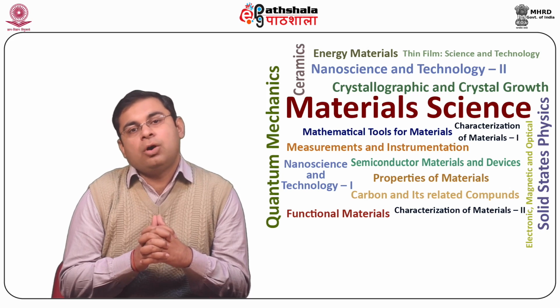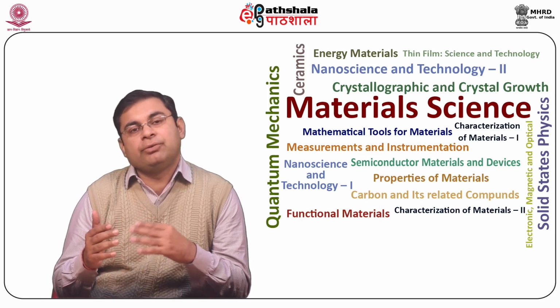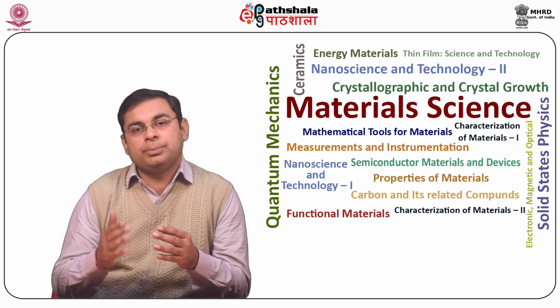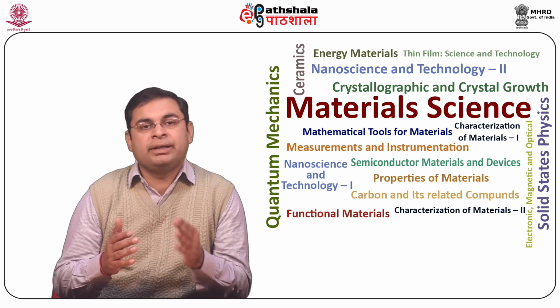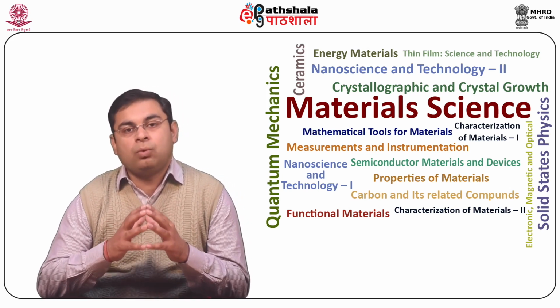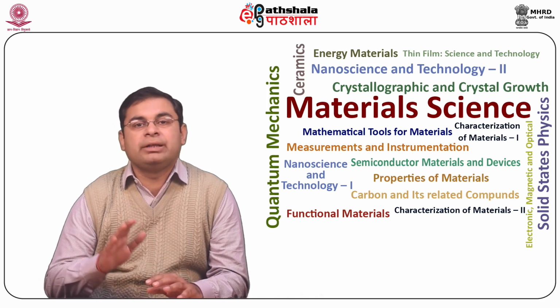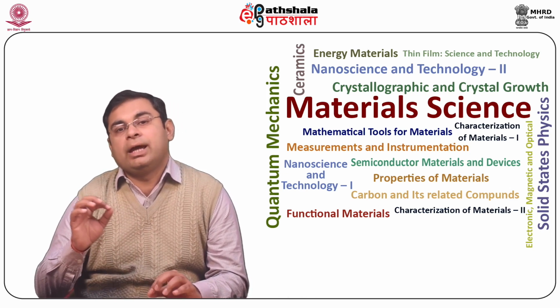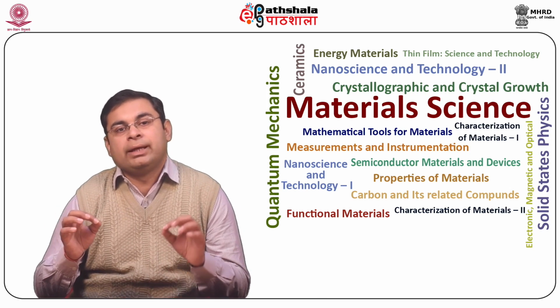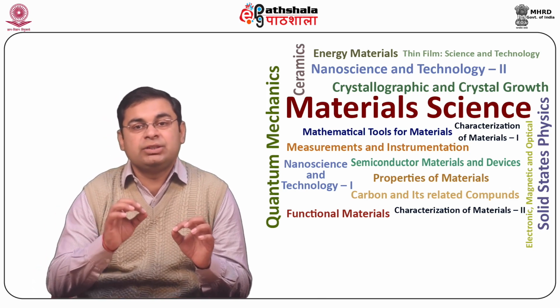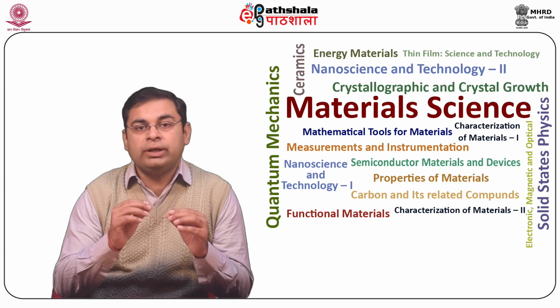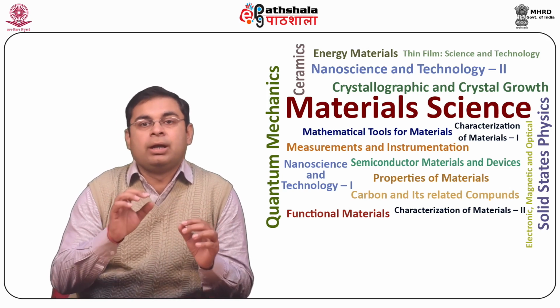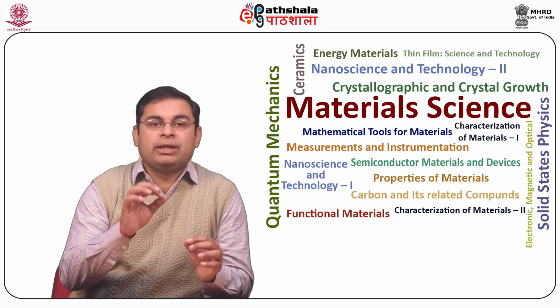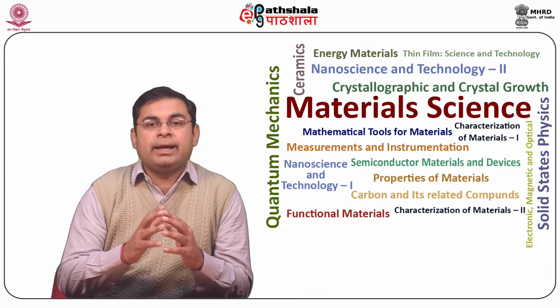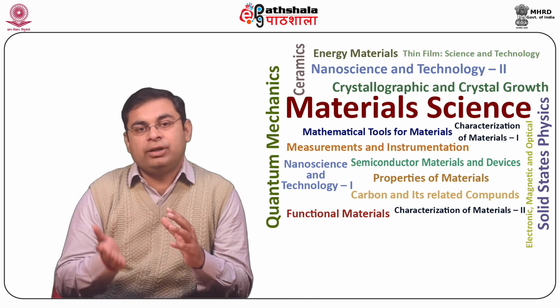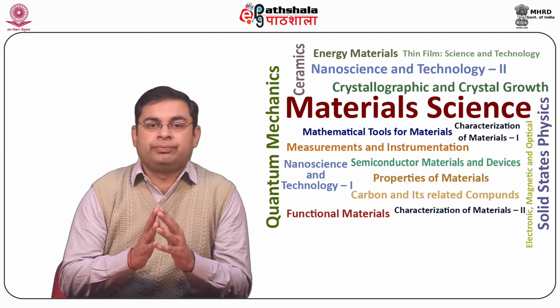Recently, the quantum Hall effect has been illustrated in very thin films at low temperature and high magnetic field conditions. The quantum Hall effect is more prominent in extremely small objects and at very low temperatures. In these conditions, the energy levels become quantized, owing to splitting of energy levels that takes place in very small structures, and the low-lying states get filled at low temperature.